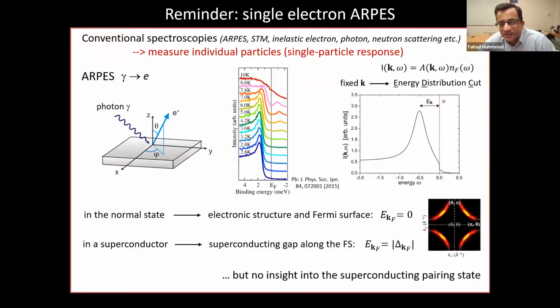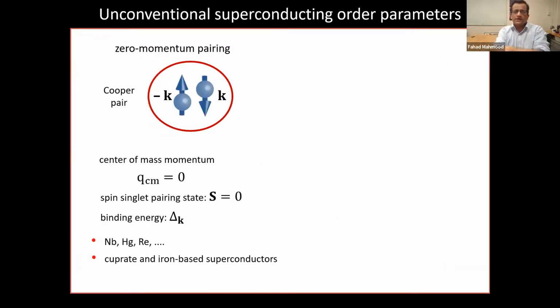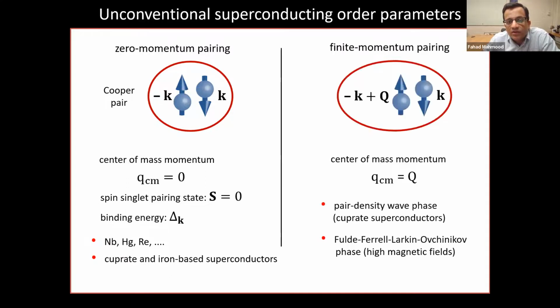But it does not really give us any insight into the superconducting pairing state. Okay, so what do I mean by that? It cannot distinguish between zero momentum pairing, where particles from opposite sides of the Fermi surface are paired with respect to each other, so your center of mass momentum for a Cooper pair is essentially zero, which is believed to happen in conventional superconductors, and finite momentum superconducting pairing. This is what would happen in a pair density wave phase, which is believed to exist in certain cuprate superconductors, or in the FFLO phase. Okay?